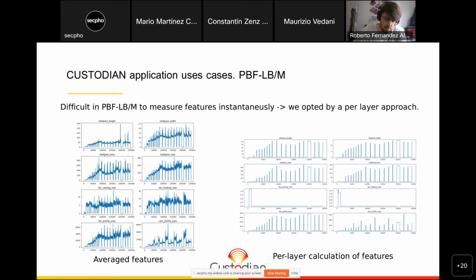So in order to be able to monitor some variables in PBF applications, we opted for a per layer strategy instead of measuring instantaneous values of each feature, just averaging the value of the different features on a per layer basis, and we only apply the control at this moment. When a layer ends, we calculate the average value of the feature during this layer, and we apply the control. In this way, we can better see the trend of the different features. It grows a lot at the beginning, then in the middle it goes a little bit down and then goes up again.